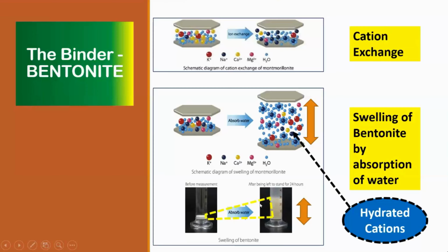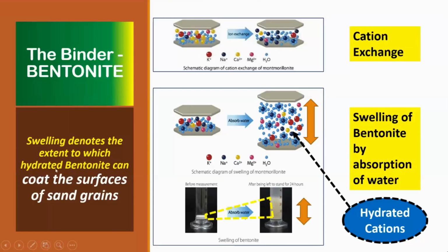So this is the test that you do to determine how much swelling capacity a bentonite has got. So this is an incoming test that you can do. After being left for 24 hours, you'll be able to see that swelling has taken place. So swelling denotes the extent to which hydrated bentonite can coat the surfaces of sand grains. What it means, when the bentonite in the powder form is a small volume, and if it is going to increase in volume when the water is mixed with it, then there is a good coverage of the sand grains by this increased volume of bentonite.